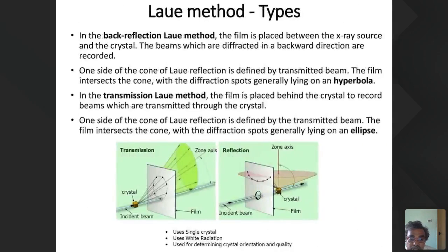There are 2 types of Laue method. One is the back reflection method and the other is the transmission method. In the transmission method, the film is kept behind the crystal to record the beams. Behind the crystal, the photofilm is kept. In the case of back reflection, the crystal is behind the incident beam, not with the incident beam. That means the back-reflected beam will be reflected onto the film. Based upon this, you are going to study your characteristics.